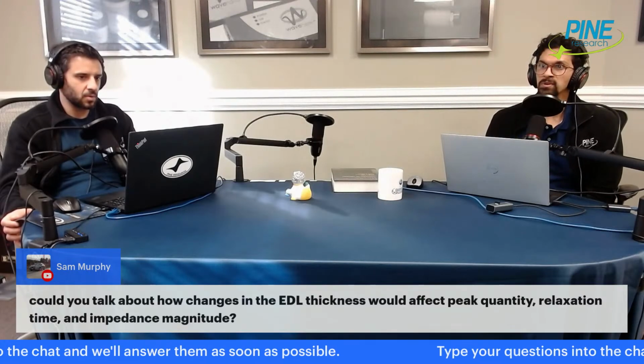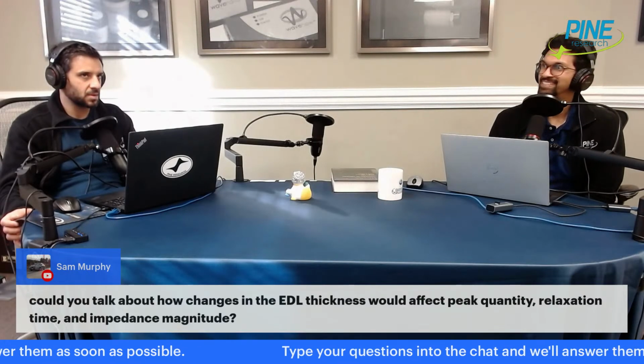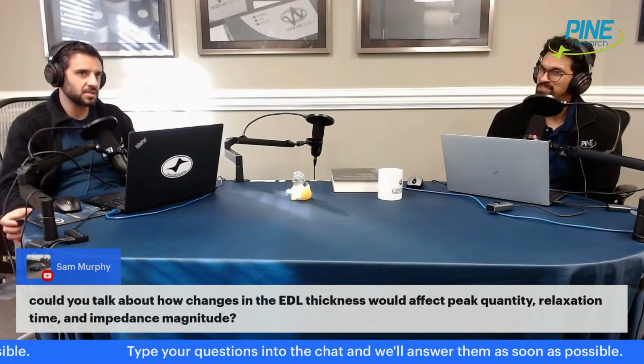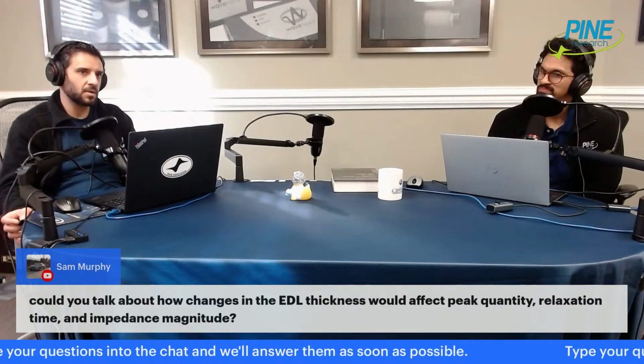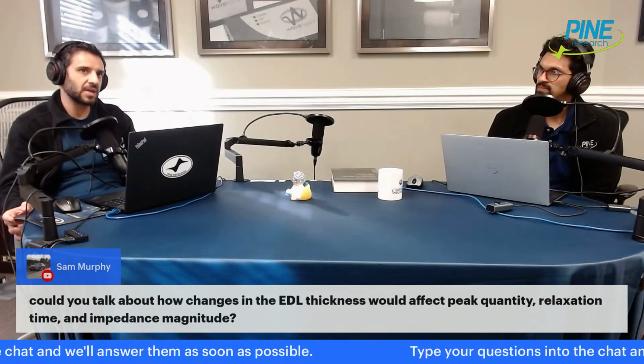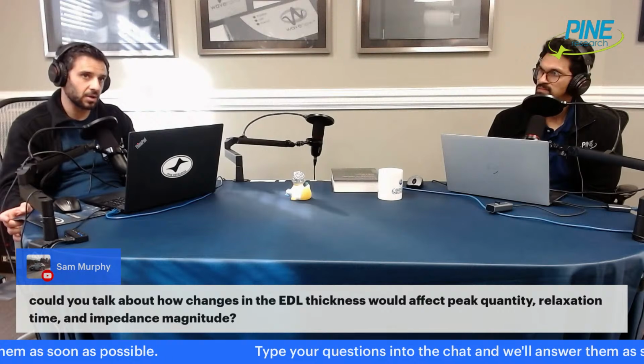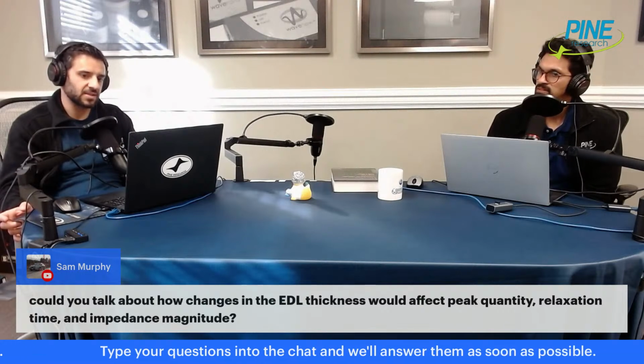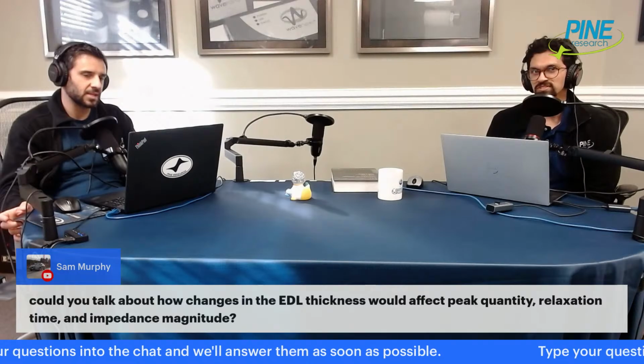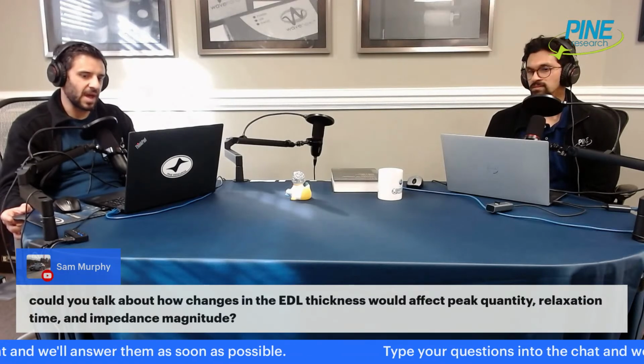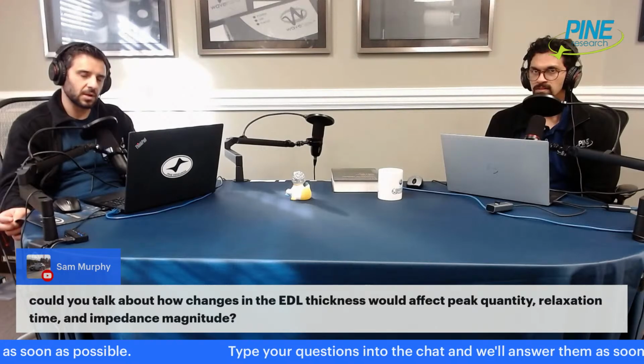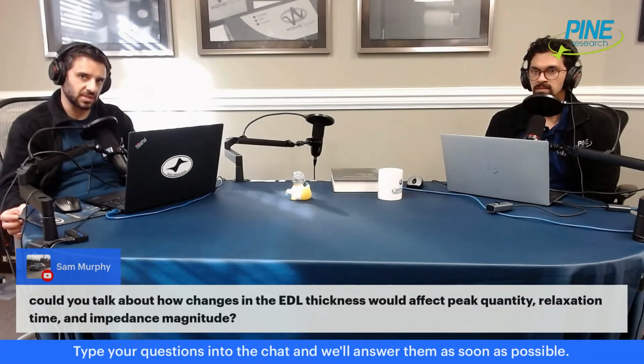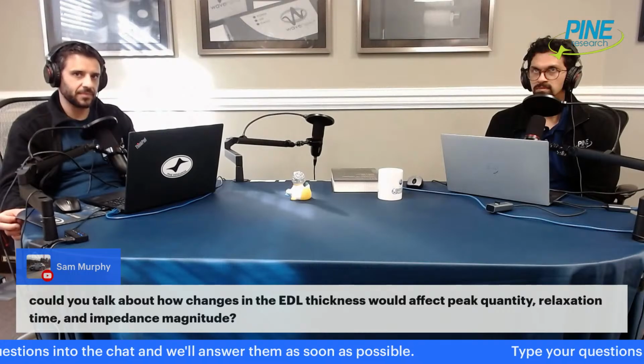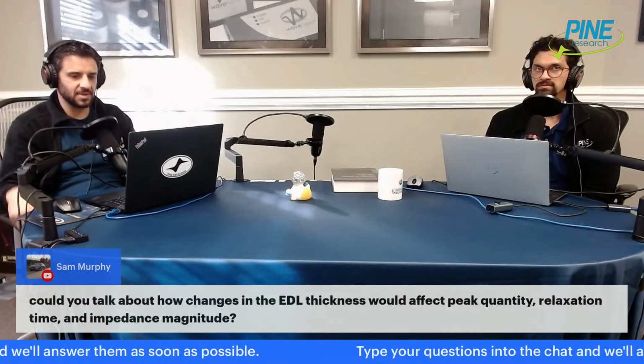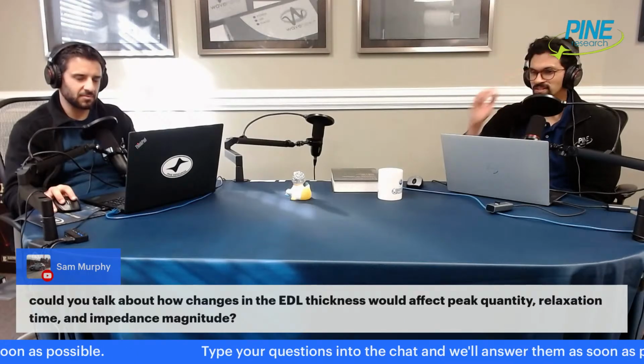Relaxation time. If it's a lower capacitance, it'll relax faster. A thicker layer, in theory, would lead to a smaller capacitance, which means the RC time constant is smaller, which means that it relaxes faster. That's my interpretation. And then the impedance magnitude would be higher. A smaller capacitor would lead to larger impedance for the same frequency, all things being equal. So that, I think, is the answer. That is our best reasoning throughout all of those things.